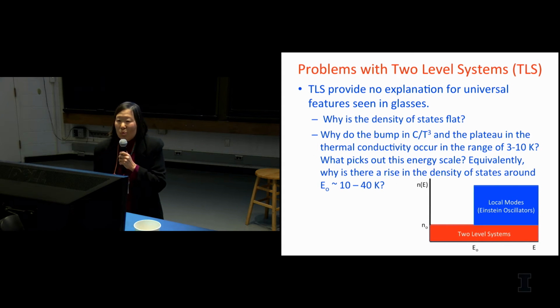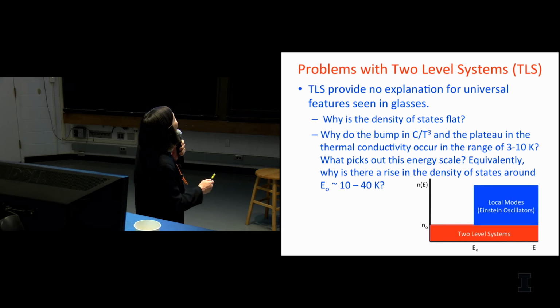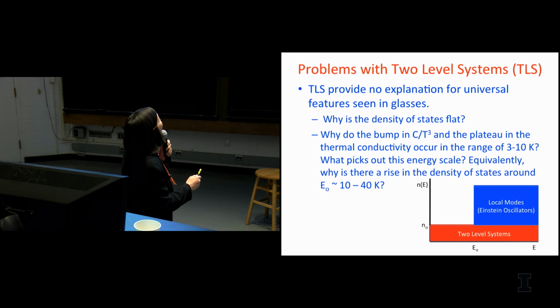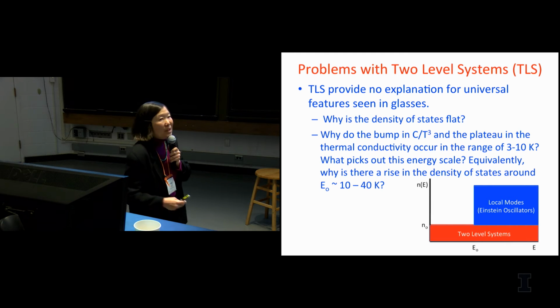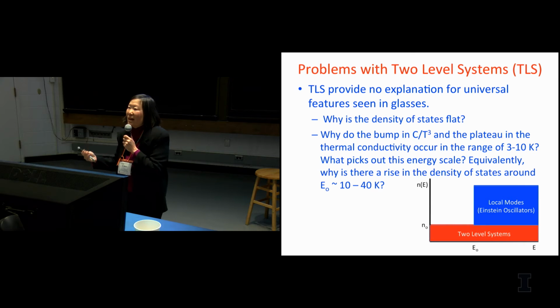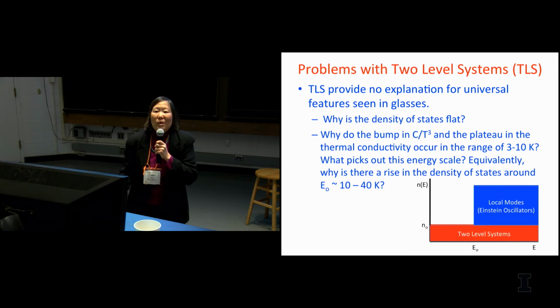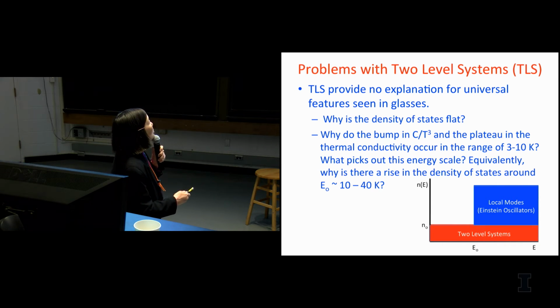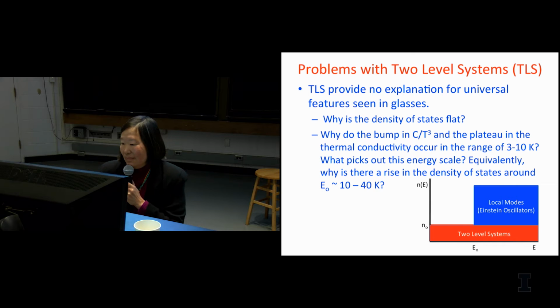Another question is, why is the density of states so flat, or pretty close to flat? And why do you have this bump in C over T cubed and this plateau in the thermal conductivity between 3 and 10 Kelvin? What picks out that energy scale? Equivalently, you could say, why do you have this rise in the density of states around 10 to 40 Kelvin? Where does that come from?